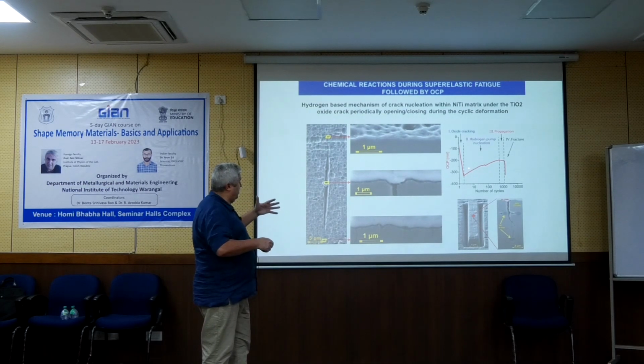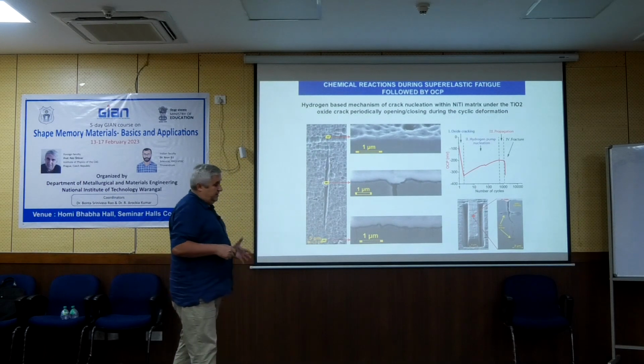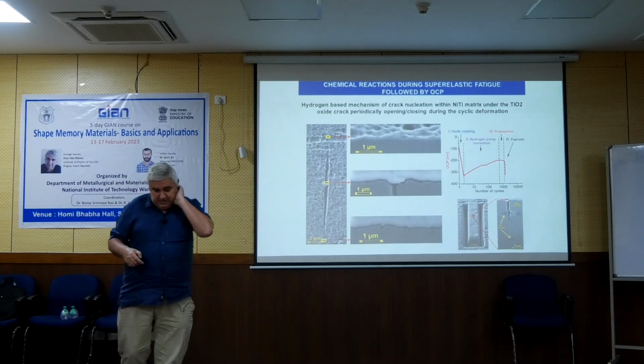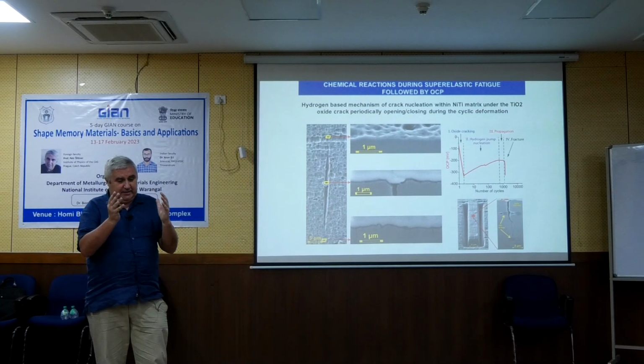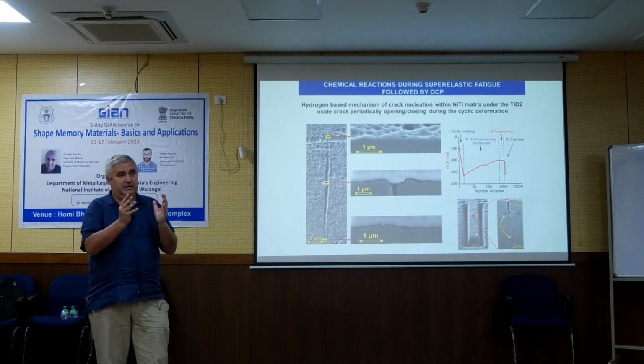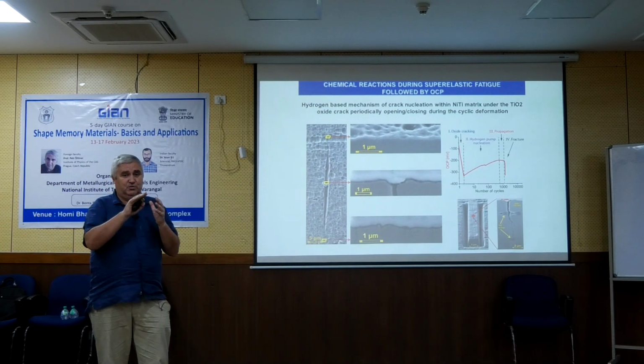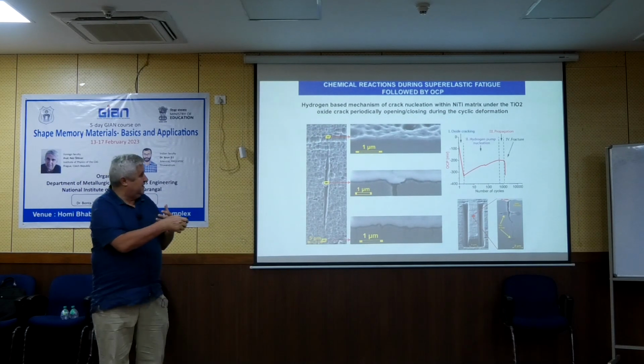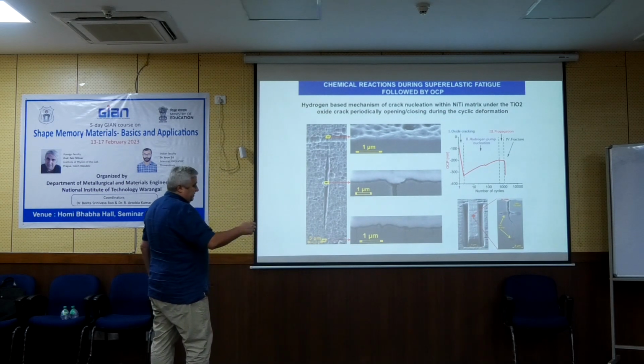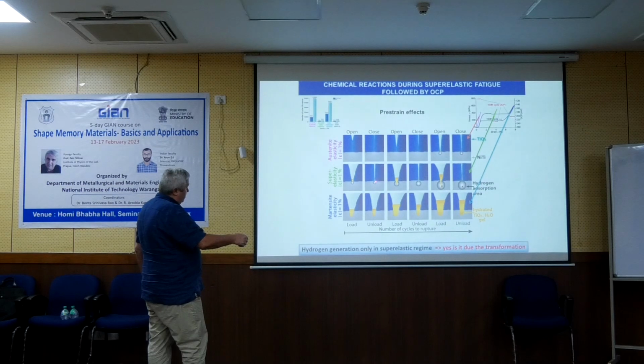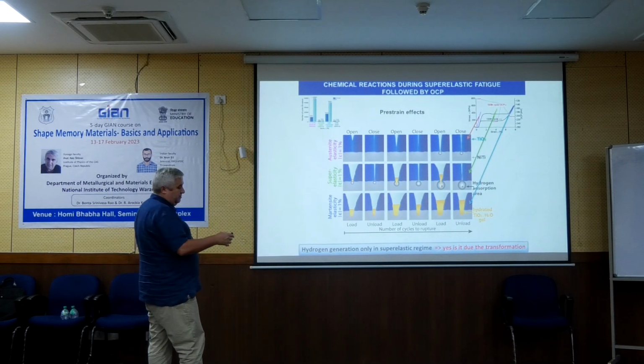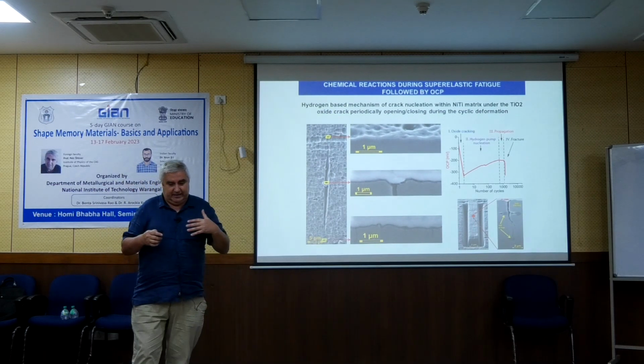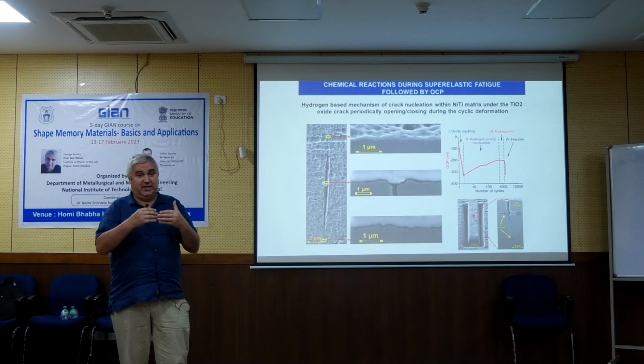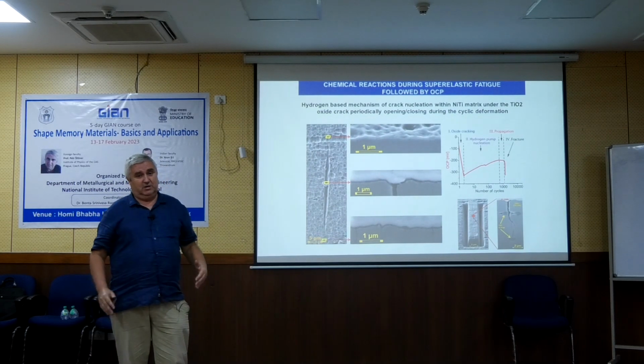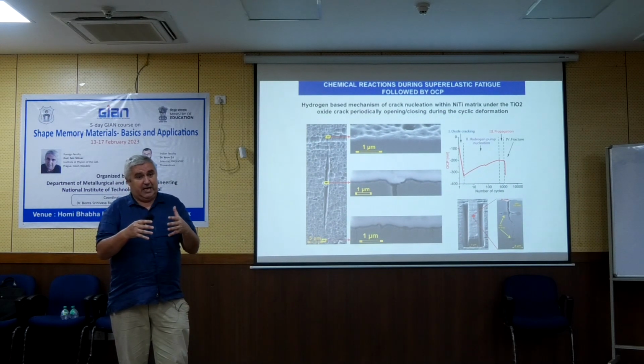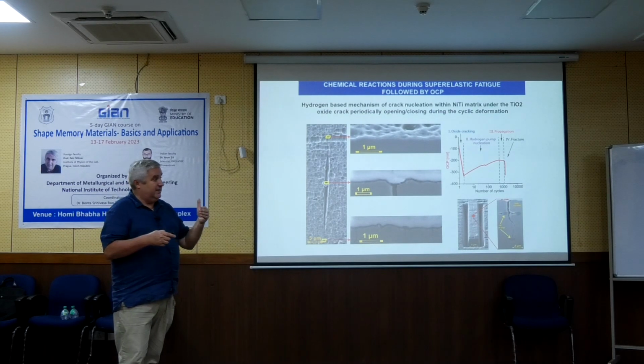But by discussion and looking at the theory we came to the conclusion that in fact this problem is this repeated passivation process at the surface, because when this happens, a lot of hydrogen is created and hydrogen is pumped into the material. So this is the passivation, and here this passivation occurs in the same place again and again for thousands of cycles. So you have actually something like an electrochemical pump which generates the hydrogen at the surface, and the hydrogen is pumped into the matrix, and after some time you find the cracks which are underneath these oxide cracks.